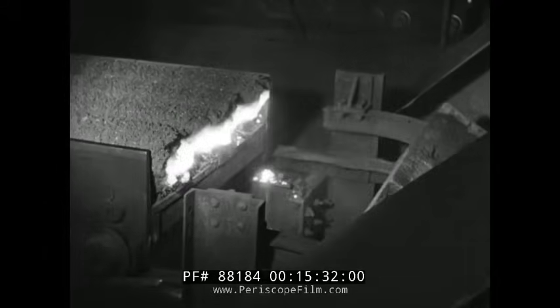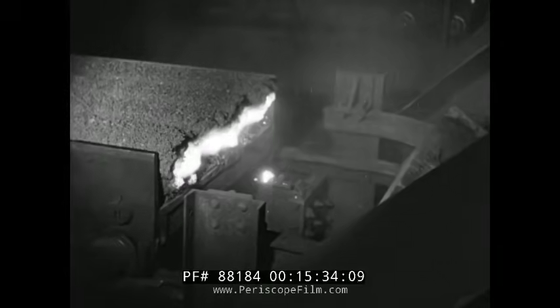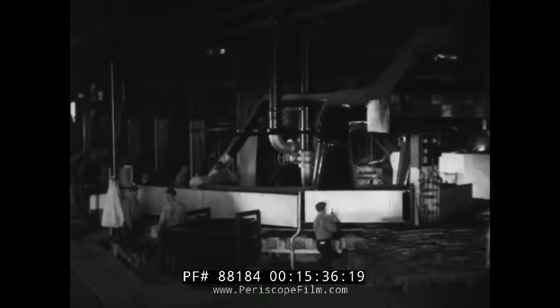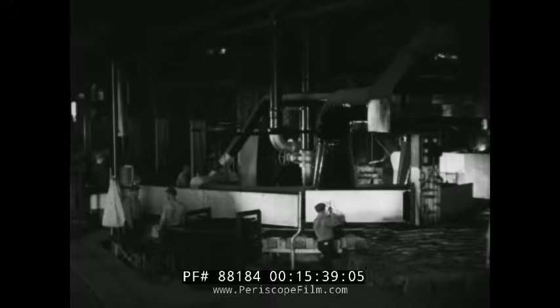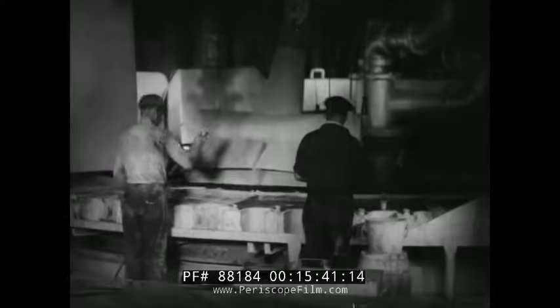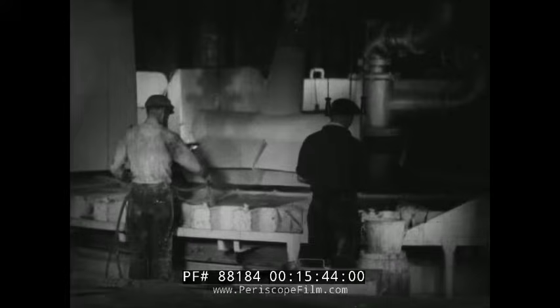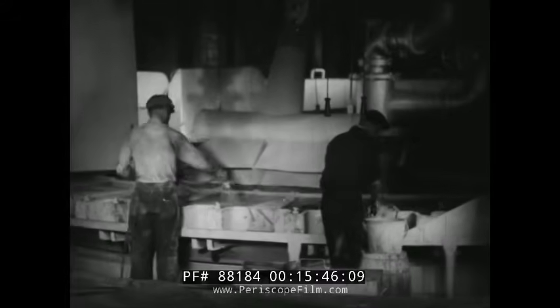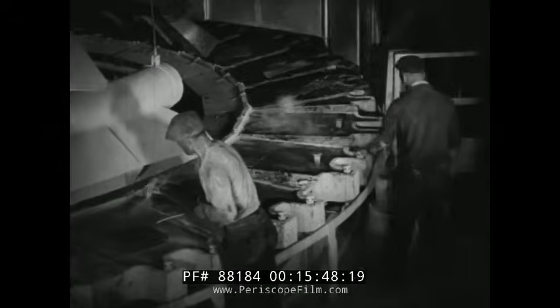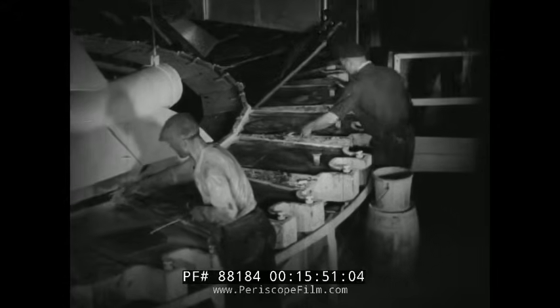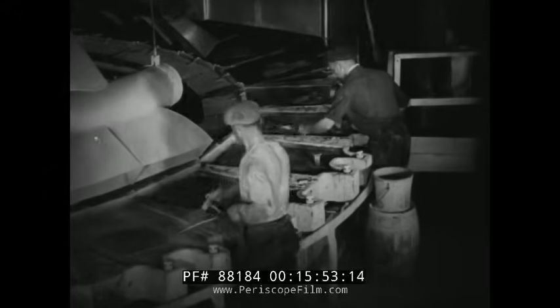To make high-purity electrolytic nickel, the washed nickel sulfide is roasted on a sintering machine. This process removes sulfur and forms a clinker of crude nickel oxide which goes into the production of nickel anodes. The sinter or crude nickel is mixed with coal and melted in the oil-fired reverberatory furnaces and in turn is tapped into the anode casting wheel holding furnace. Each mold is carefully cleaned and prepared before receiving the metal.